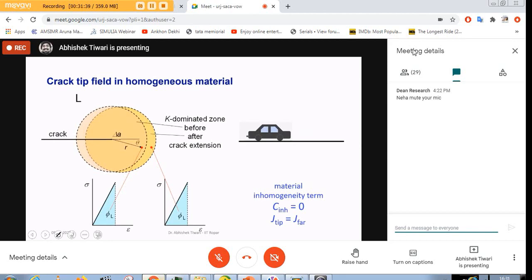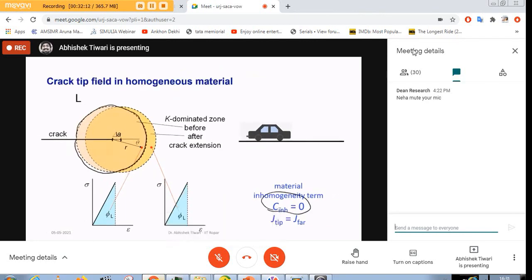So let us assume that we start from this position and the material is completely homogeneous, and this is our contour. So what do we do? We calculate all the configurational forces in this contour and we sum it up and we find out the J integral value. And that value is some value. Then crack grows to this extent. We take the same size of contour which has moved now because the crack tip has moved, and then we again sum all the configurational forces and we again get the same value. So there is no inhomogeneity term. And whatever energy we are providing to the system is reaching the crack tip. And the analogy I give you is that I'm driving a car and I'm not changing any parameters of my driving and I'm riding on a flat road. So this situation is like that.